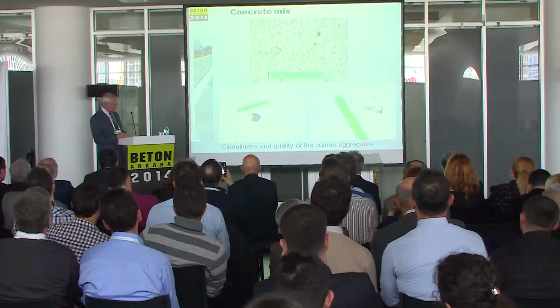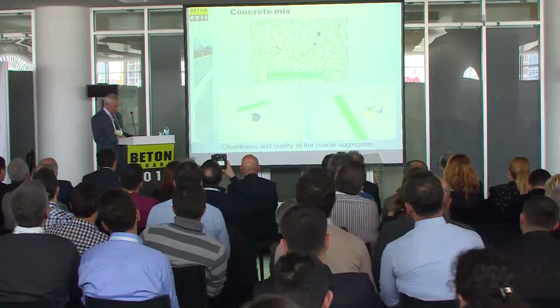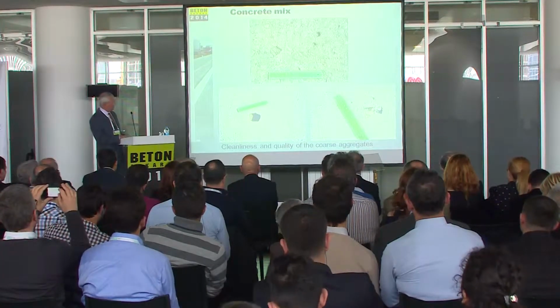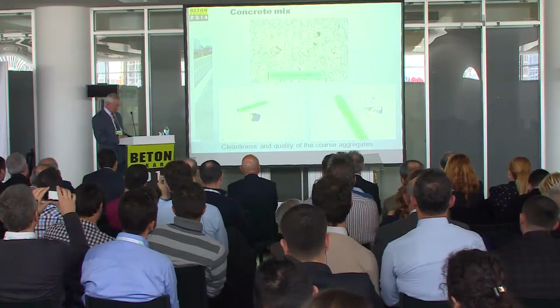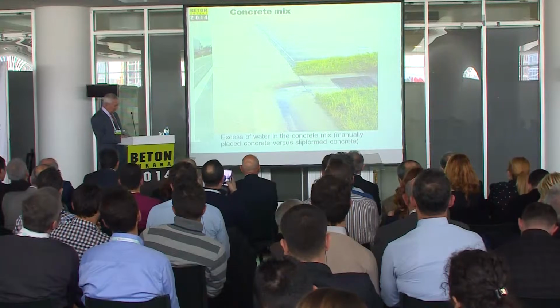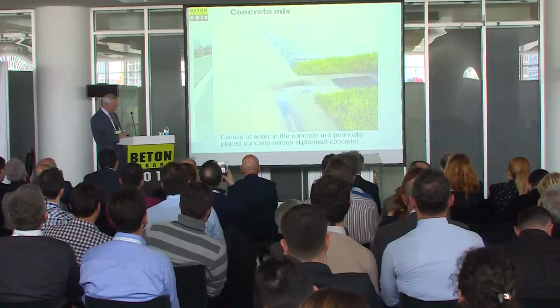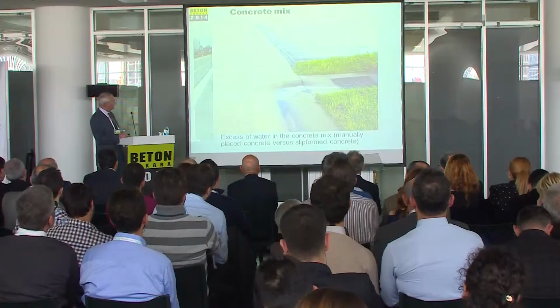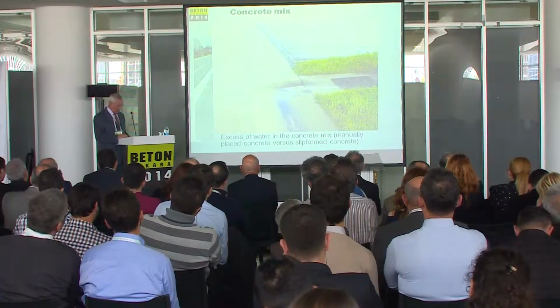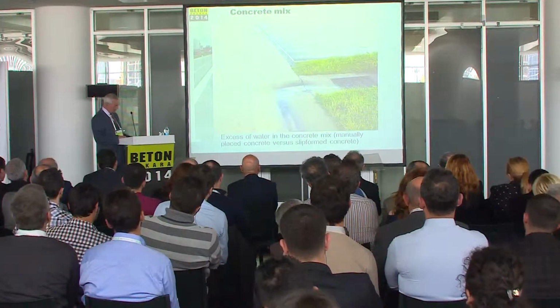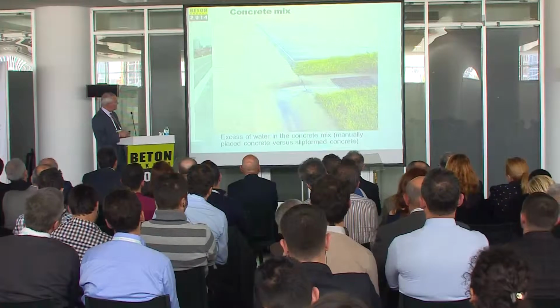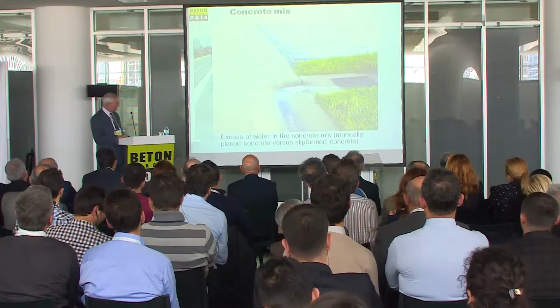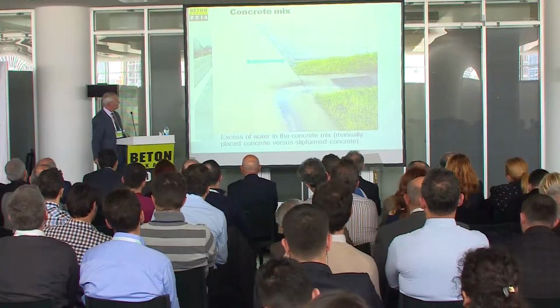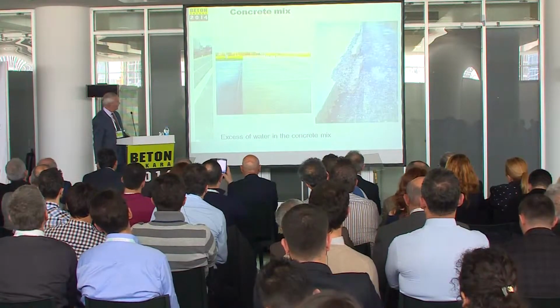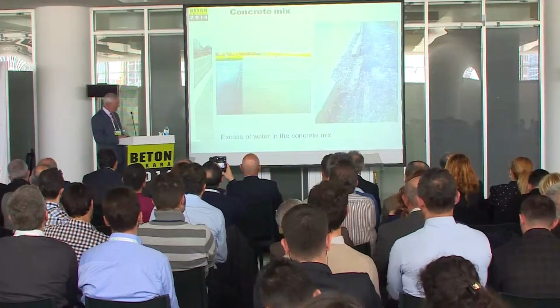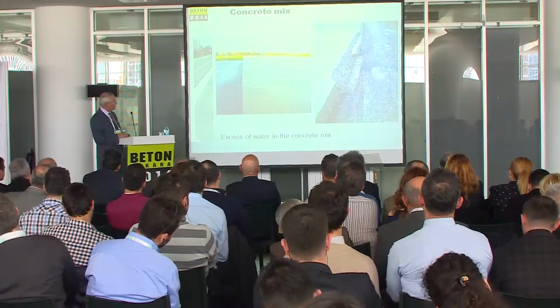In a concrete mix, cleanliness and quality of coarse aggregates are essential to avoid local and unpredictable damages. Manually placed concrete versus slip-formed concrete, with excess of water in the concrete mix, and the state of the surface shows a rather bad final quality. The same excess of water in the concrete mix: surface damage and edge collapse.